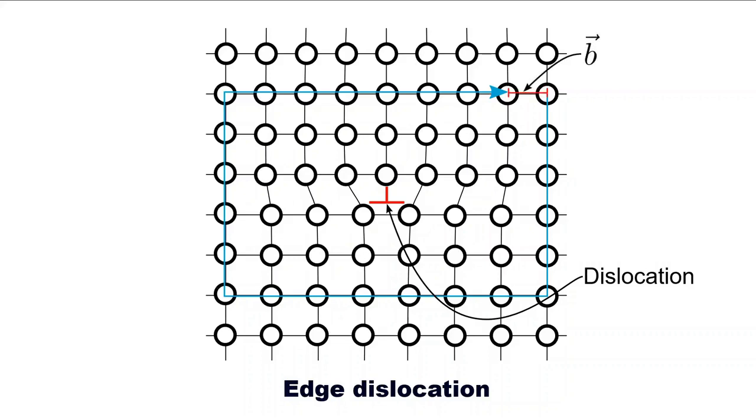The distance needed to complete this circuit around a dislocation is called the Burgers vector. The magnitude would be 1 lattice spacing, and the direction would depend on the convention employed to render the circuit. If one were to use my convention of clockwise and finish to start, the Burgers vector's direction would point left to right. This exercise may seem a little artificial, and it may not be immediately apparent why it's necessary to define and employ a Burgers vector.